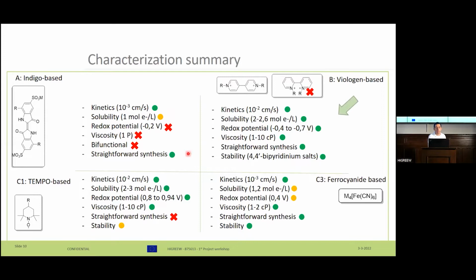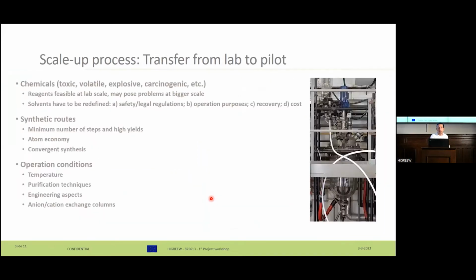In the case of the catholyte, still we have the two options, the tempo derivatives and the ferrocyanide. And in this sense, the main limitation of the tempo derivatives is the synthesis, which is not straightforward and requires 4 to 6 steps. In the case of the ferrocyanide, the main limitation is the solubility of the compound, which can be somehow solved by using ammonium cations, and as well the redox potential, which is significantly lower than the nitroxyl radicals. At this step, then we decided to evaluate all those compounds in the part of the scale-up with the collaboration with COC, that is a company that is helping us on this process.